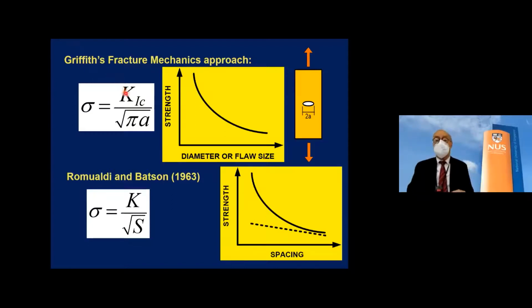And of course, in the case of the fracture mechanics condition that Griffith had developed, the strength of the material, if you want, is some kind of constant. This constant is called fracture toughness, mode 1 cracking, whatever. But anyway, some kind of constant divided by the square root of pi a. Pi is 3.14, and a is half the crack size, assuming you have a flaw crack. The initial assumption was a penny-shaped crack. But anyway, half the crack length, say, in a concrete concept is used. And effectively, Griffith showed that this relation holds.